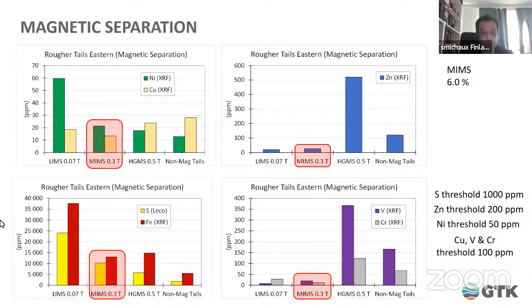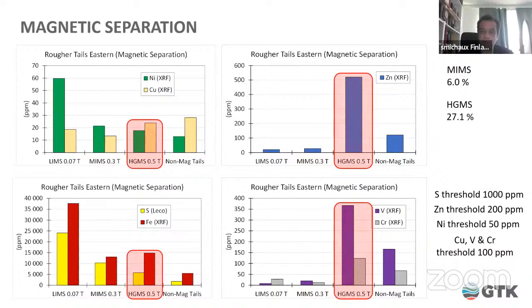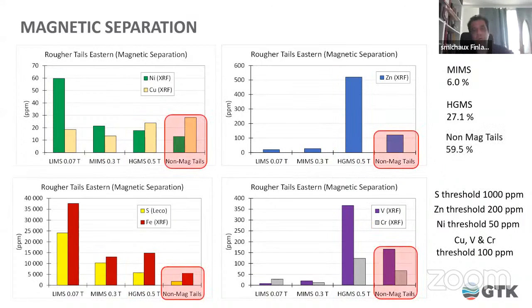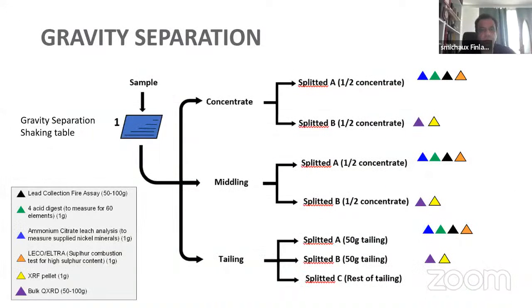Sulfur is still quite... if we did complete magnetic separation in the tailings, we're just below the threshold. But that represents way too much mass because the high magnetic separation represented 27.1% of the mass, and that's just not practical. So what we're going to do is assemble all the options together and recommend a combination of things. So it might be gravity, then magnetic, and then leaching, or thereof. But each one will have a engineering logistics profile.